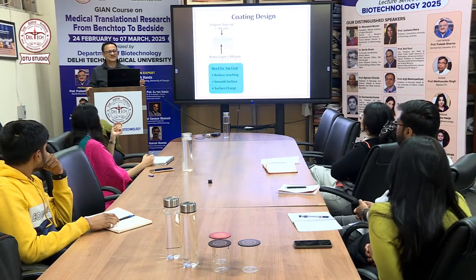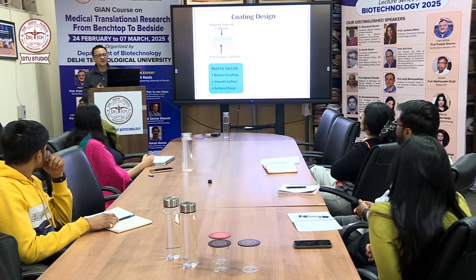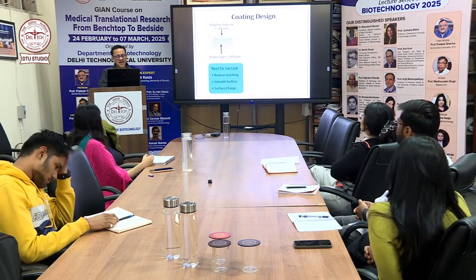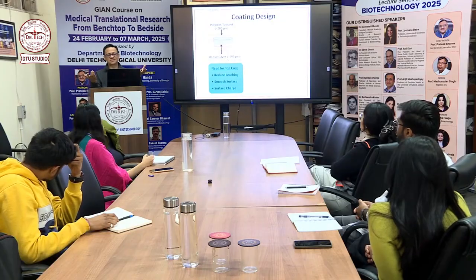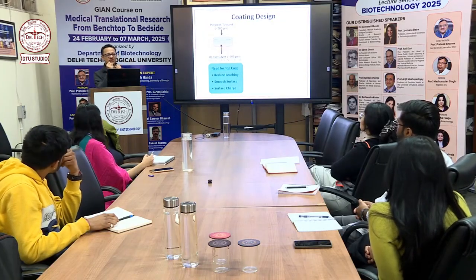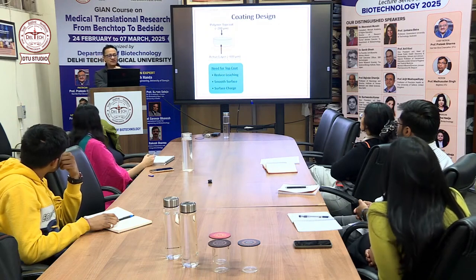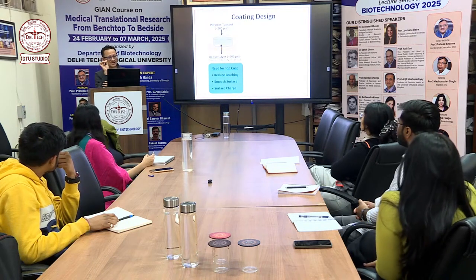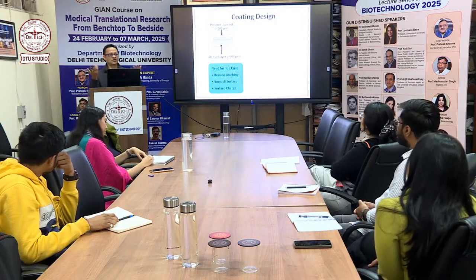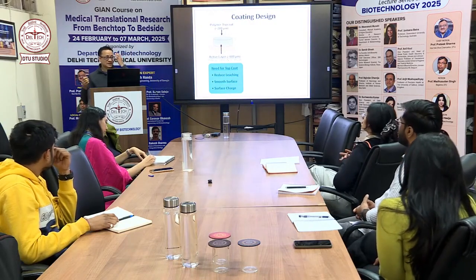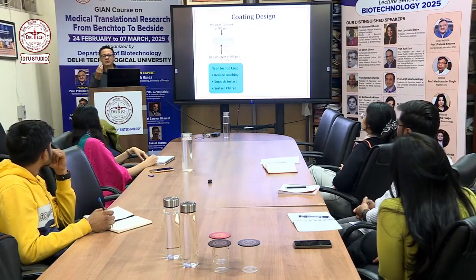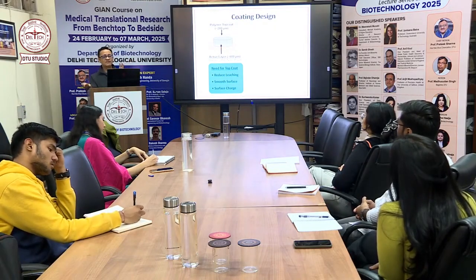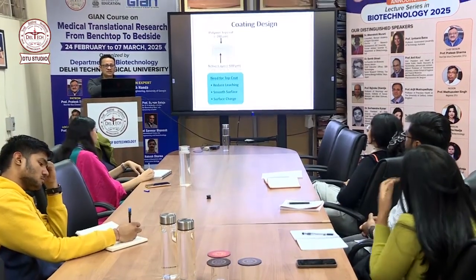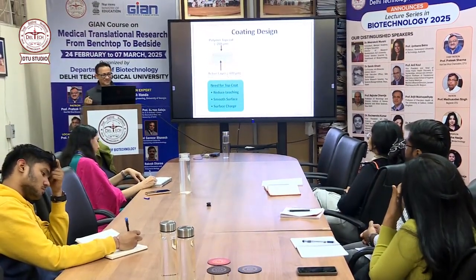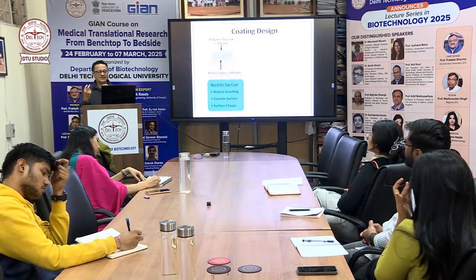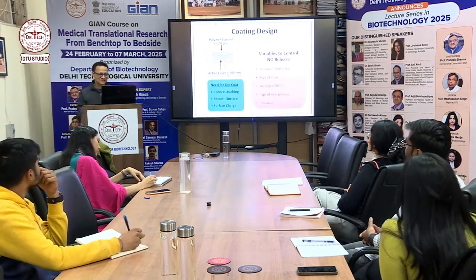Yes, the quantity of each: the quantity of PLGA, the quantity of diazeniumdiolate, and the polymer. I mean, the polymer will be the maximum, yes, because that's giving the structure and strength to the material. The other two things are, see, PLGA has to be very little because we don't want it to start dissolving and your catheter is dissolving now, right? diazeniumdiolate, if it's like a powder that's nitric oxide releasing. If you add too much diazeniumdiolate in a catheter material, it might start becoming brittle. So now we had to play with what's the ratio of all these things.